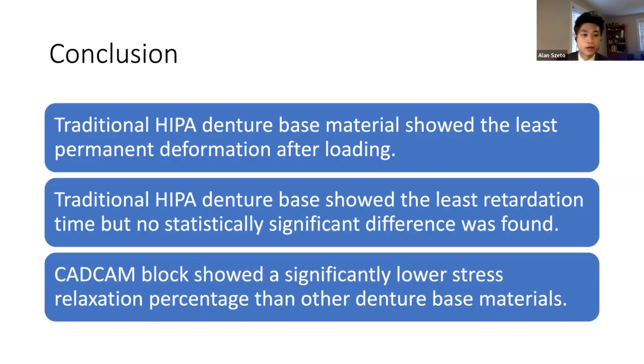And with the data that we got, we came up with three conclusions. The first one is traditional HIPA denture base material showed the least permanent deformation after loading. Second, traditional HIPA denture base material showed the least retardation time, but no statistically significant difference was found between the groups. And the last one is CAD/CAM block showed a significantly lower stress relaxation percentage than other denture-based materials.